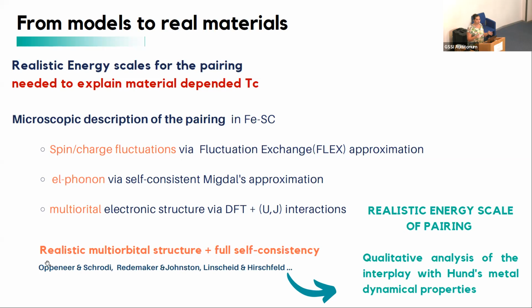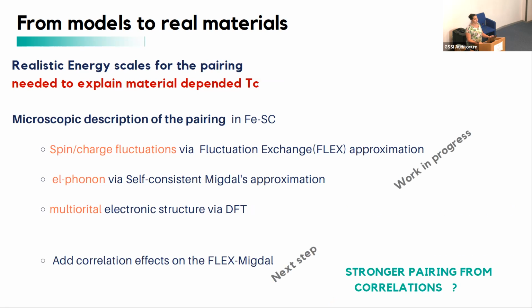And with respect to the current situation, there are several flex codes that do more or less the same. The main disadvantage is that certain of these codes are working with very simplistic band models. Others are accounting for the multi-orbital structure of the electronic bands, but are not fully self-consistent. So we want to overcome this limitation and see essentially what is the realistic energy scale of pairing. And this will give us already a qualitative estimate of the interplay that we can have with the Hund's metal dynamic properties. And the last step, of course, is to introduce the effect of correlation in this flex Migdal Eliashberg code. That is an open question that would also be important for accounting for electronic correlation in electron-phonon systems.